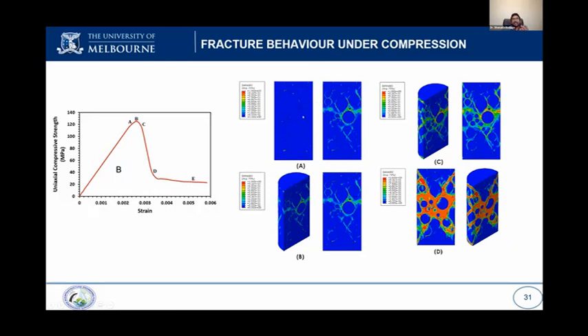So the failure starts from the ITZ. ITZ in high strength concrete is actually better than ITZ in normal strength concrete, but still it is the weakest point. So it's not a problem in the mortar, it's not a problem in the aggregate, but it's a problem in ITZ. So if we can improve the ITZ, it means we can further improve the strength of concrete.